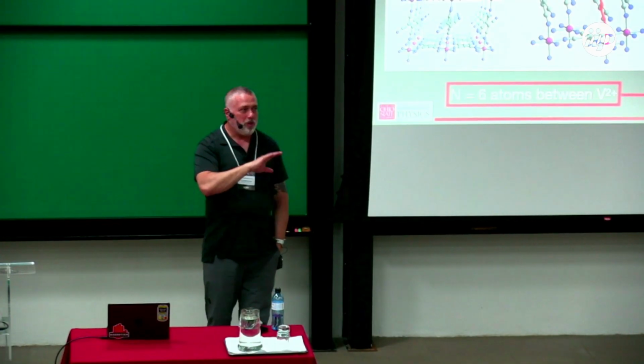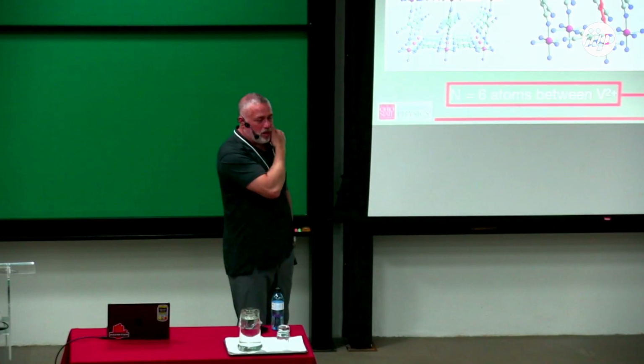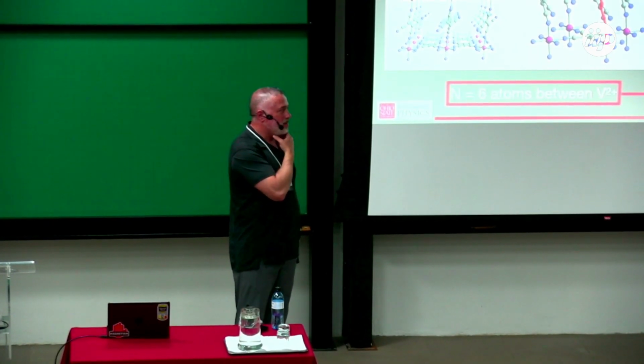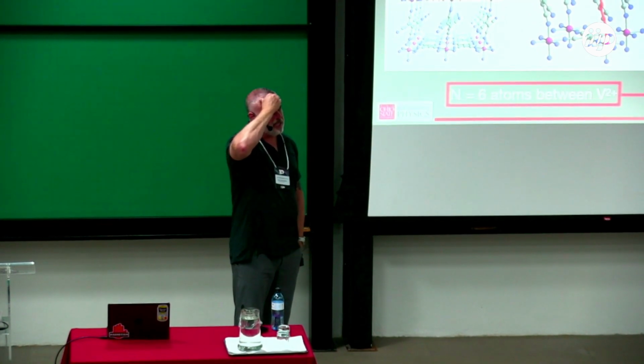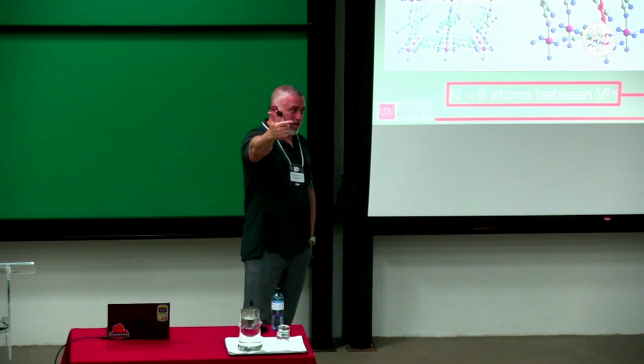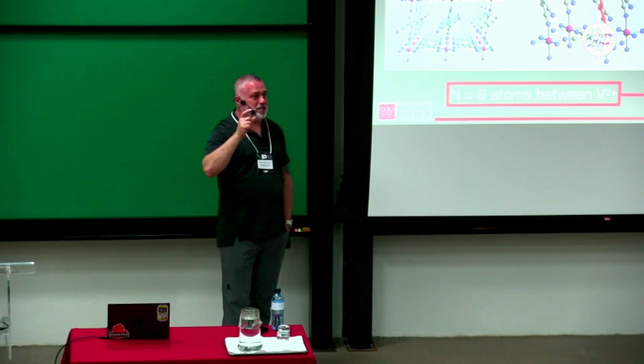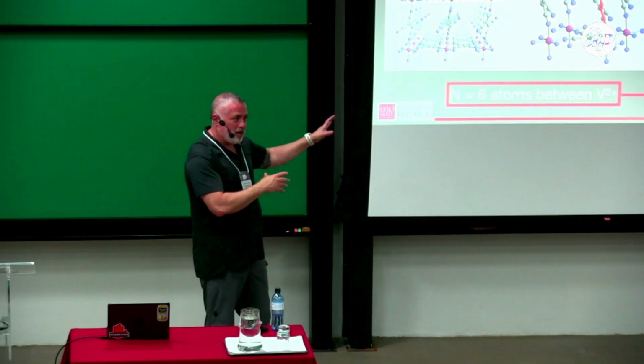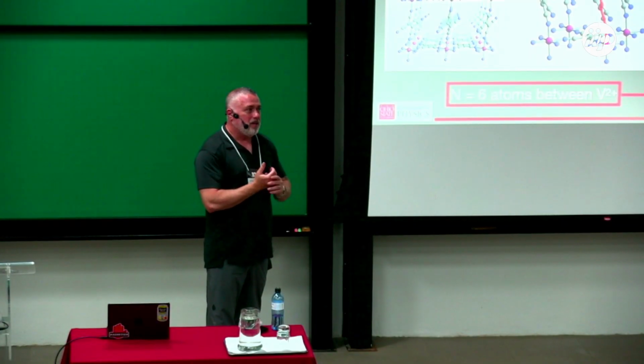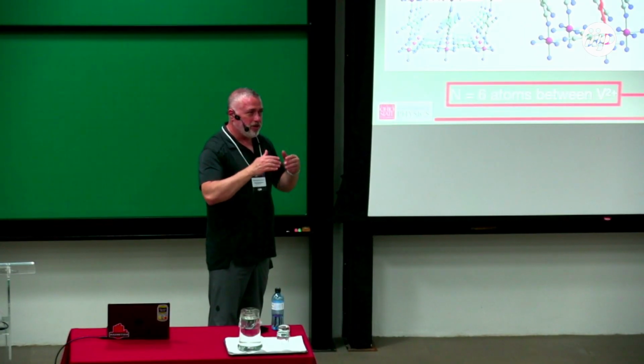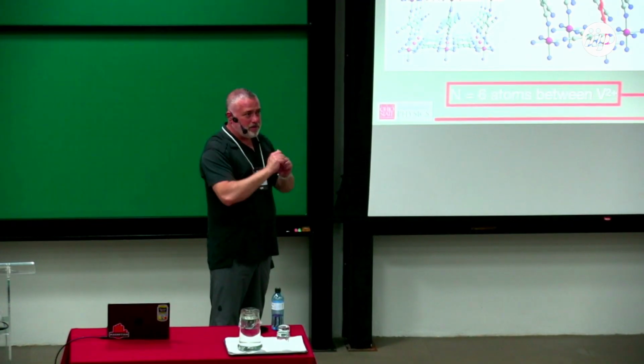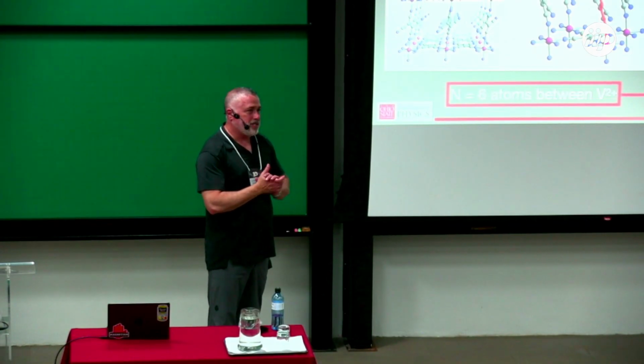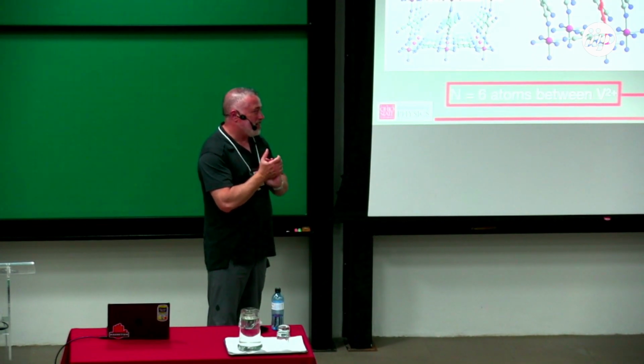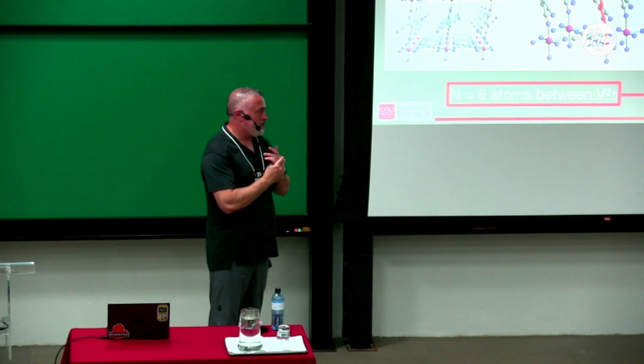I think, and so far this is based on modeling coming out of the Spenzabek work, so we haven't measured it directly yet, but I think reasonable level of confidence that what we're seeing is that the lifetime of the magnons may in fact be longer than YIG, but the propagation length is shorter, and those effects cancel out to give roughly comparable diffusivity. But in terms of the coherent propagation that you'd want to do for very long distances, it's not clear the magnons have very long range. I don't know, Mike, collaborators may have a different take on that. So essentially, the spin wave velocity is a lot smaller than it would be in YIG. Yeah. And that's related to that exchange stiffness. And so the distance is not as long.